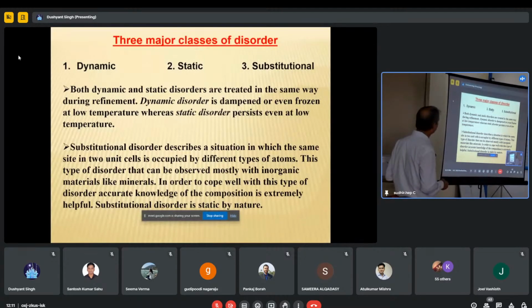Substitutional disorder describes a situation in which the same site in the two unit cells is occupied by different types of atoms. Suppose I have a substitution of a phenyl ring where a chlorine is attached to the phenyl ring. Suppose this is the chlorine atom. In one unit cell, it is a freely moving substituent on the phenyl ring. In one unit cell, it is sitting like this, in another unit cell, it is like this. So in that case, it is a substitutional disorder. Chlorine is coming 50% occupancy at the right side, 50% occupancy at the left side. So we call it static disorder or substitutional disorder.